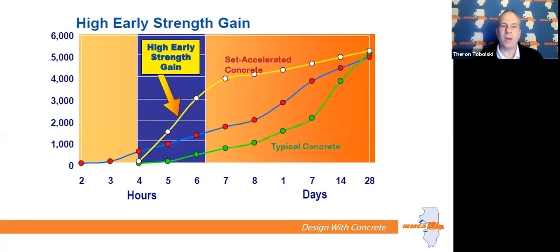We talk about accelerators, right? We showed you how you could put a retarder in the concrete to slow the concrete down, but you can also put an accelerator in the concrete to speed it up. Maybe you want higher release strength to open up a concrete pavement sooner rather than later. So you can see the green line is a typical concrete mix with no accelerator in it, compared to the yellow line that has accelerator in it.